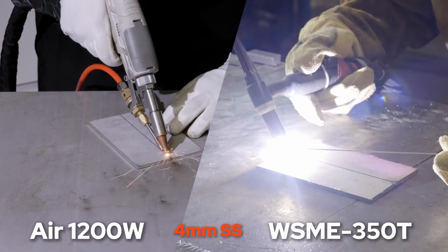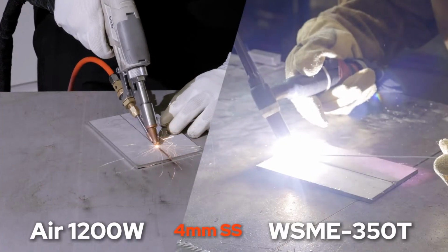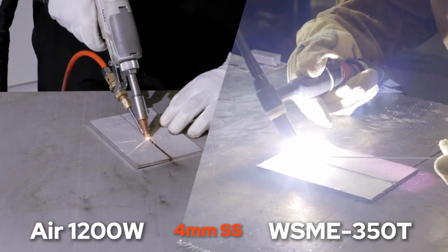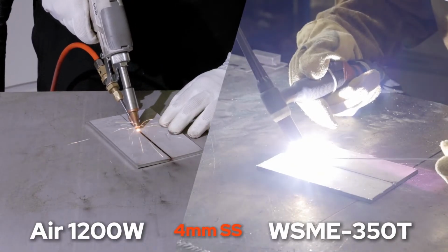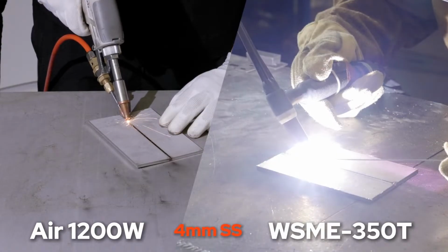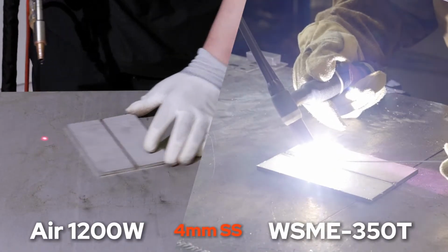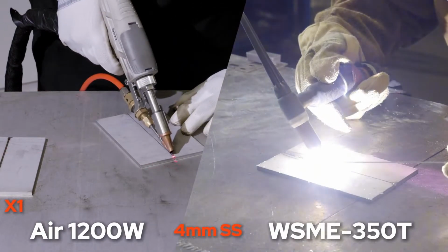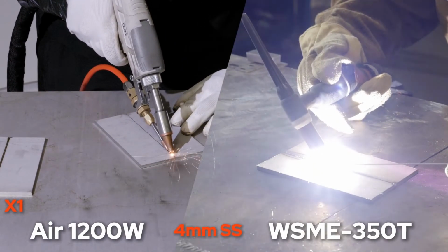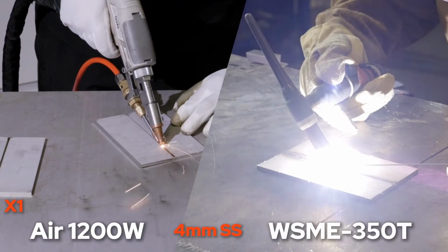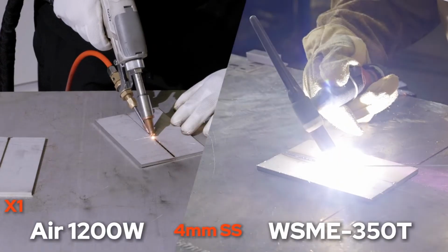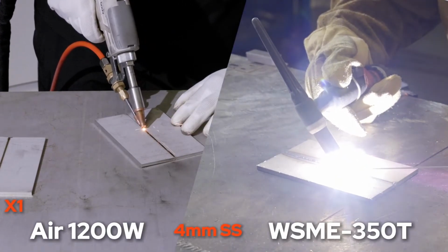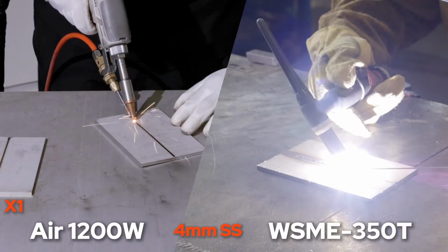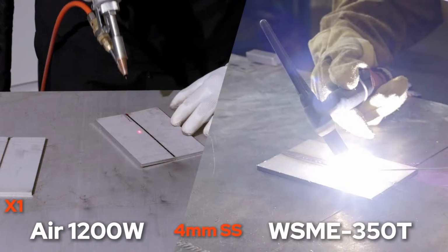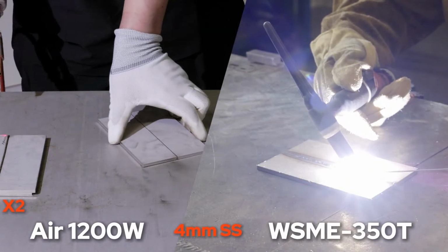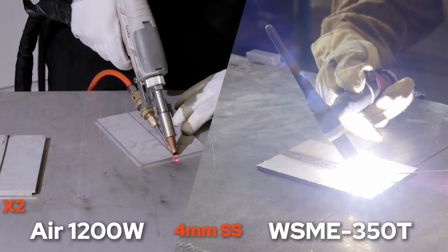Alright, here we go. On the left, you will see handheld laser welding in action, and on the right, TIG welding using the same materials and same conditions. Laser speed is eye-opening, isn't it? It's clearly leading the race. That's right. With 4mm stainless steel, laser welding moved significantly faster with smooth torch movement. TIG welding, on the other hand, needed a much slower travel speed and careful coordination to get proper fusion. In real-world production settings, we typically see laser operate at 3 times the speed of TIG across various materials, sometimes even more.